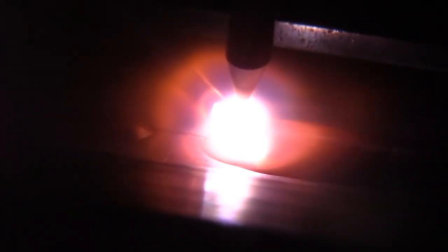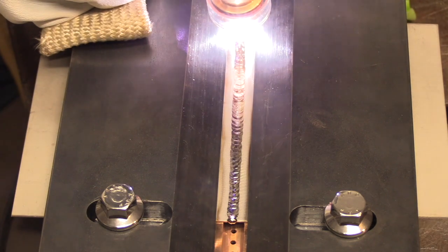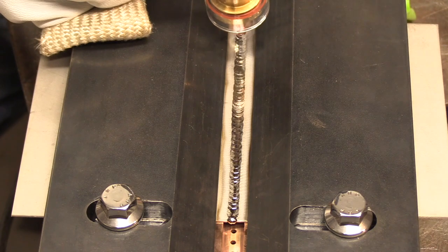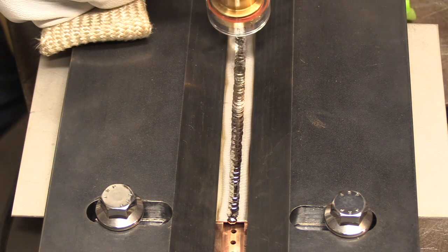This is a titanium test joint just like you would take for an aerospace job in a fixture with backup gas on the back side. No discoloration at all and that's what you're after with titanium.